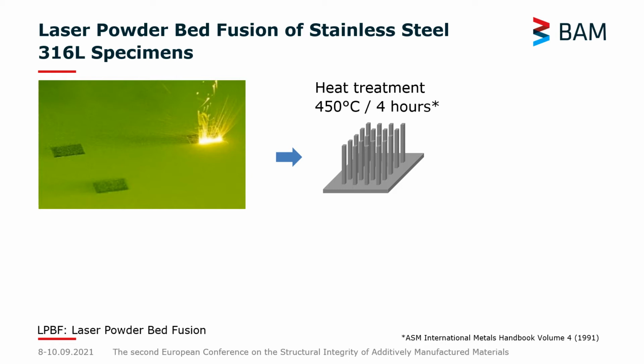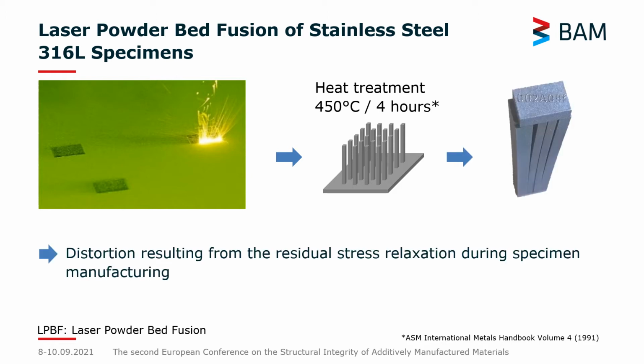Now, unfortunately, once we started cutting different shapes or extracting different geometries from the generic as-built shape, we faced distortion. So the residual stresses that were still remaining on our part were so high that the material started bending. And now we have to ask ourselves, although we applied a heat treatment, what are the remaining residual stresses, especially when manufacturing different shapes or cylindrical shapes from this starting block and where we don't see any distortion? What are the residual stresses remaining in this part?